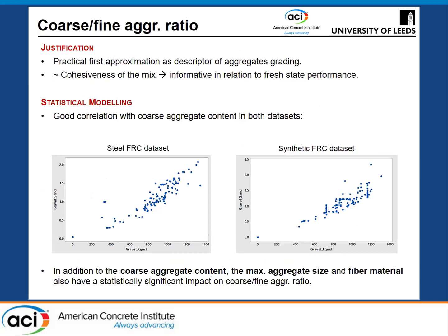So looking at those three things, I started looking at different relationships that we could try and predict in the mix. And the first one is the coarse to fine aggregate ratio. Why? Because I thought that it's interestingly quite a good proxy to the grading of the aggregates in the mix. And that has a huge impact on the fresh performance, and is something that we don't think about enough when it comes to fiber reinforced concrete.